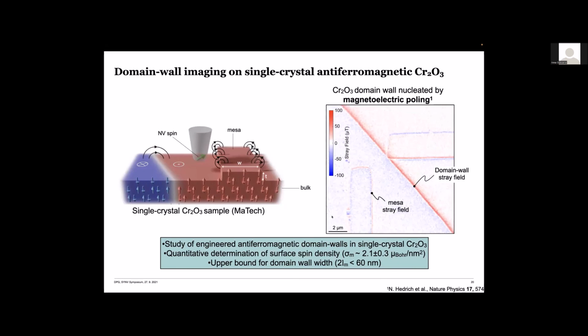So here you see an example of a scanning NV magnetometry image of this single crystal of chromia. What we did again was to pattern the surface into mesas so that we get some stray fields out even in a part of homogeneous magnetization. And these are these mesas that you see here. And then by, again, magnetoelectric poling, we were able to introduce these domain walls into the sample. I should say without such poling, there were no domain walls, and that's not a surprise because after all, for a bulk single crystal antiferromagnet, there is no energetic reason to form domains.